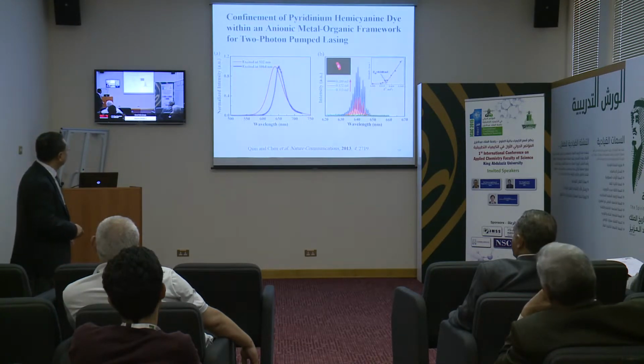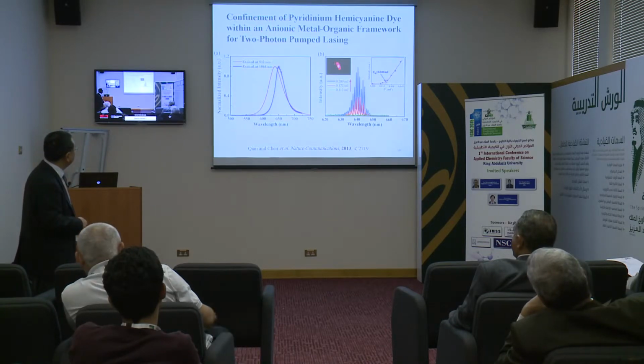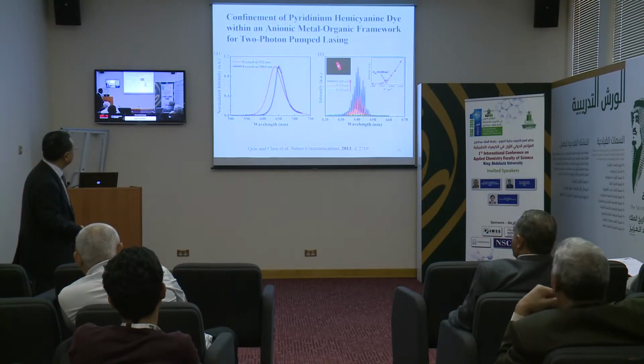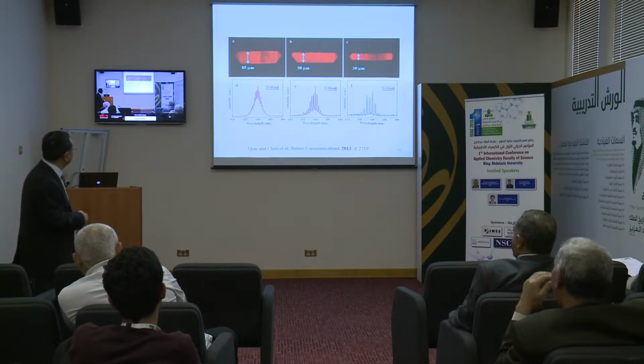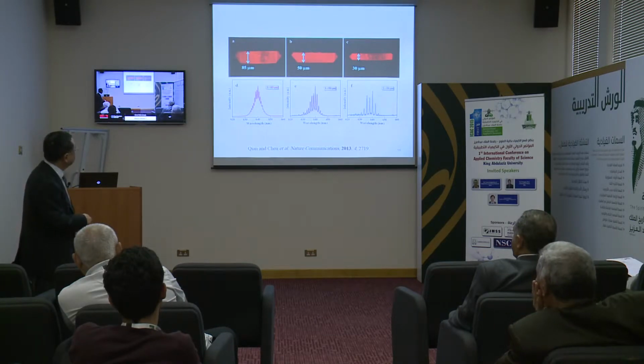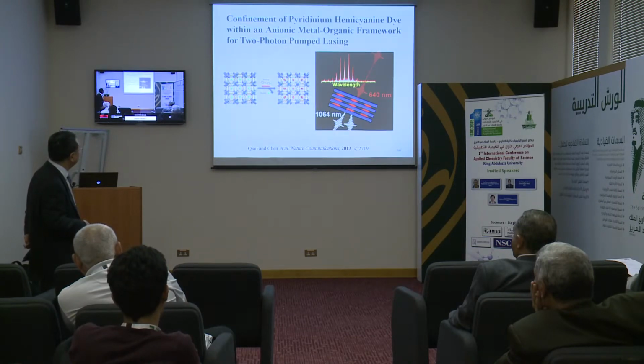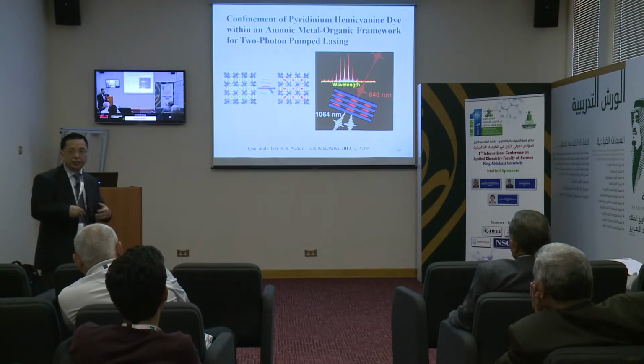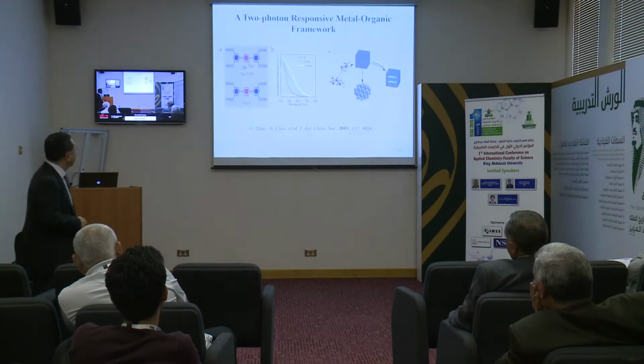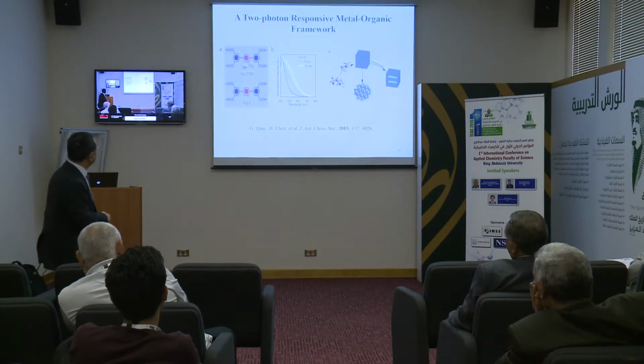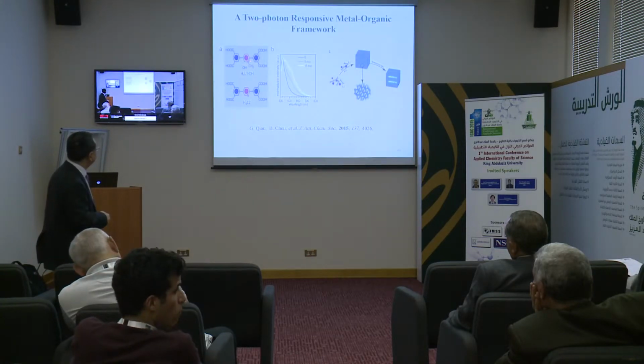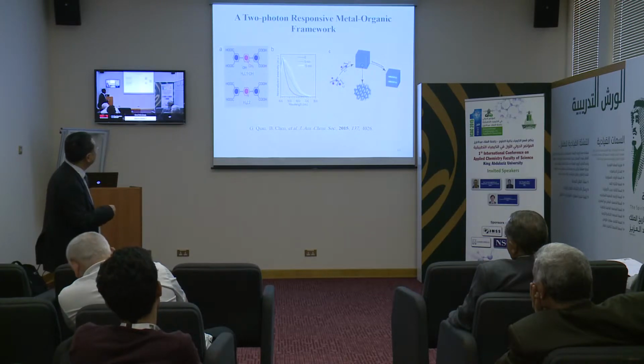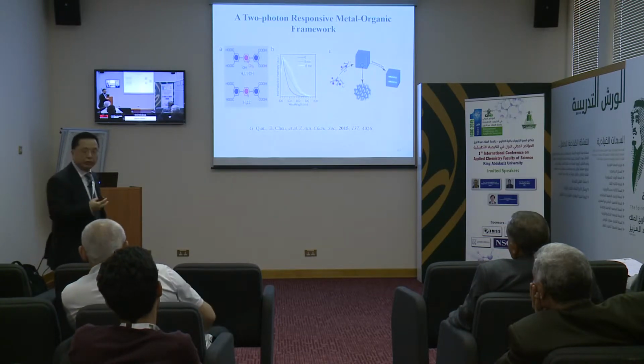So we realize the lasing functions, two-photon pumped lasing is quite stable, and you see this lasing, of course, is dependent on the length of these crystals, and this is the first example for this finding. So apparently, these low energies can generate high energy lasing. So I think it's quite interesting, and also we can use a photoactive organic linker. So this is basically only responsible to the two-photon UV.